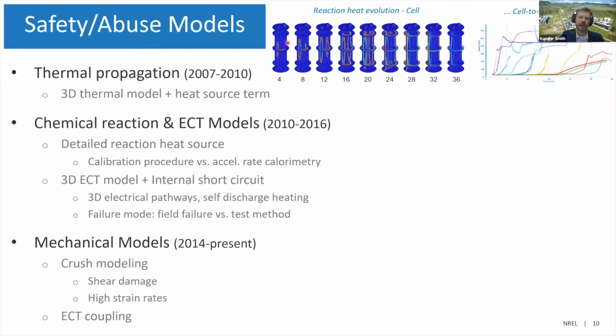The foils are in a wound structure, so it goes around the circumference of the cell. And so you can see the propagation going both in the circumference of the cell as well as vertically in the direction of the foils. That describes the evolution throughout a cell, and it can be important to know how that evolves so that you can potentially evaluate safety features such as shutdown separators that melt at certain temperatures.